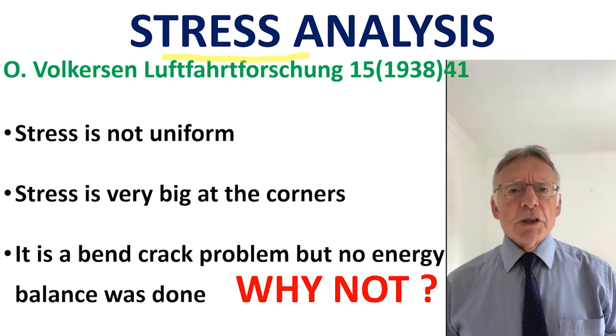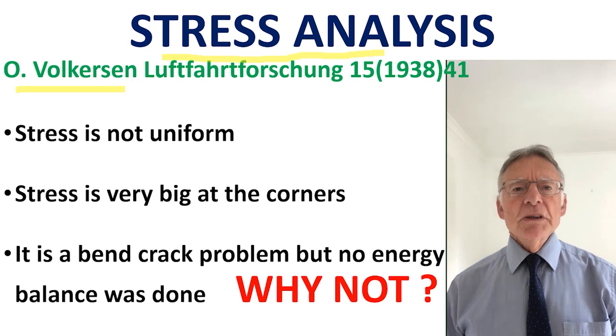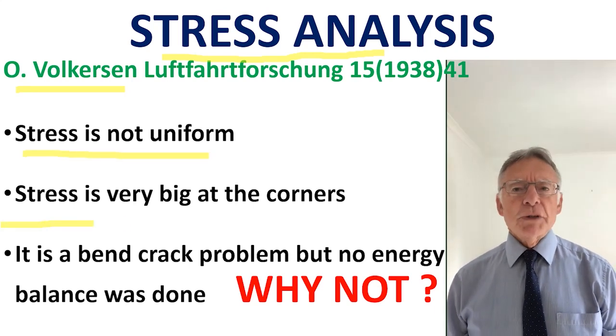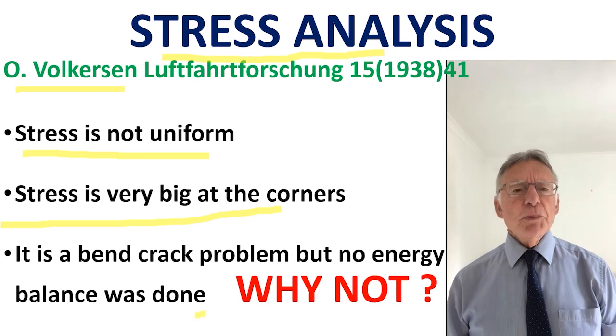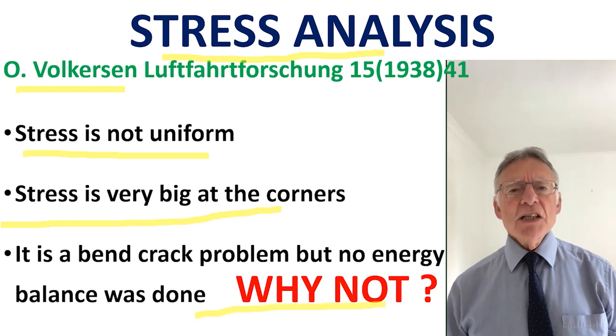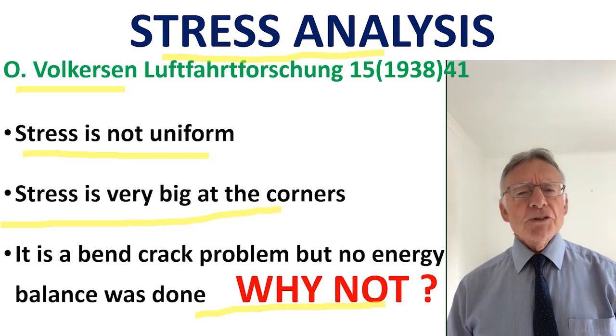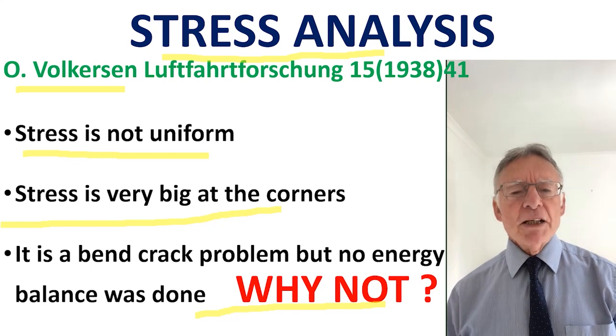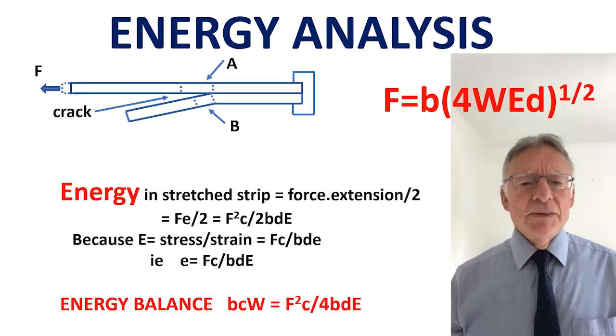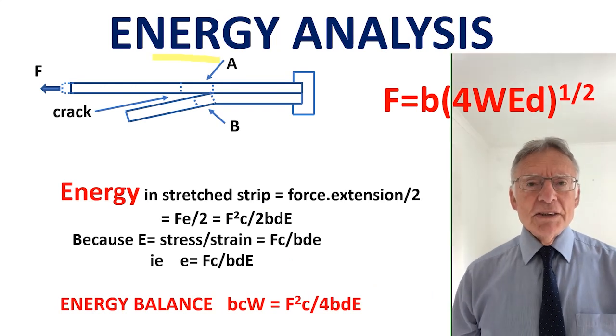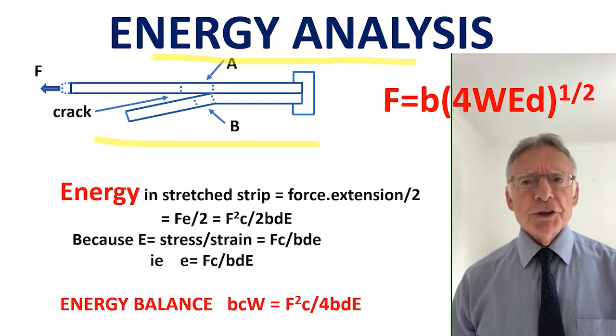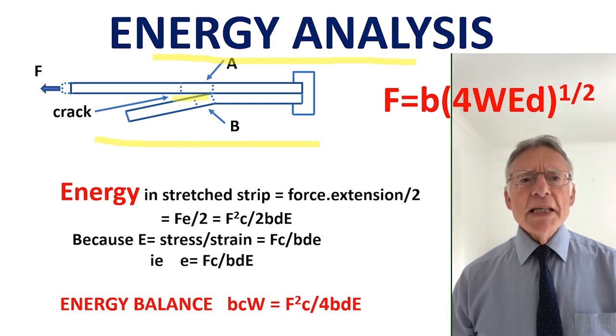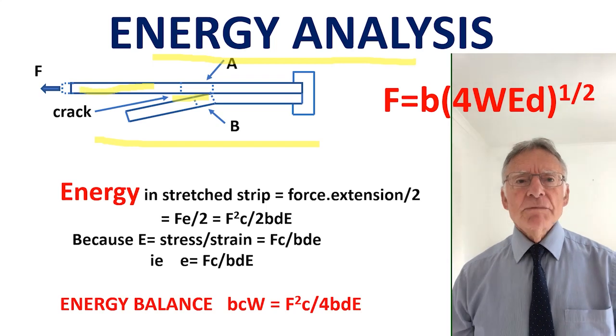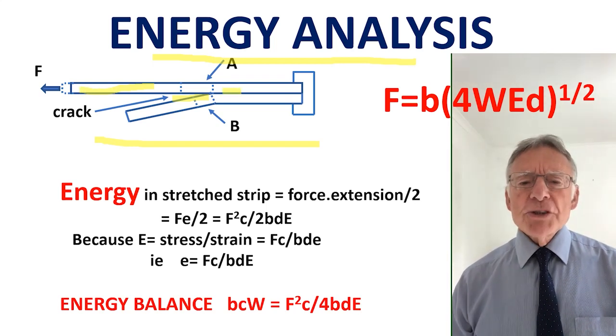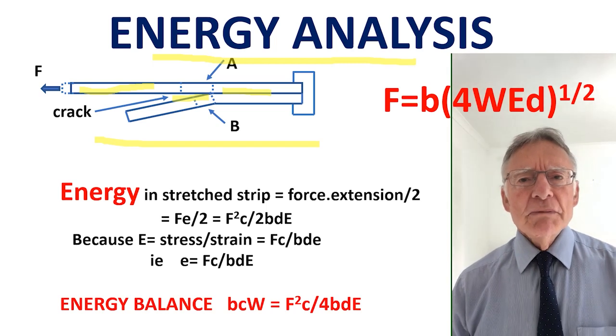The stress analysis for the joint was done 82 years ago by Volkersen, showing very high stresses at the corners, as you'd expect. But why did Volkersen not apply Griffith's energy argument? It was 18 years after Griffith. Most engineers still wrongly believe that the strength argument applies. No, when cracking occurs, you must use the energy argument. The energy analysis is easy if we consider a long half joint like this with one crack. The main energy is in the elastic stretched sheets. At the crack tip, the energy is constant as the crack runs along, and so it disappears. It can't drive the crack.